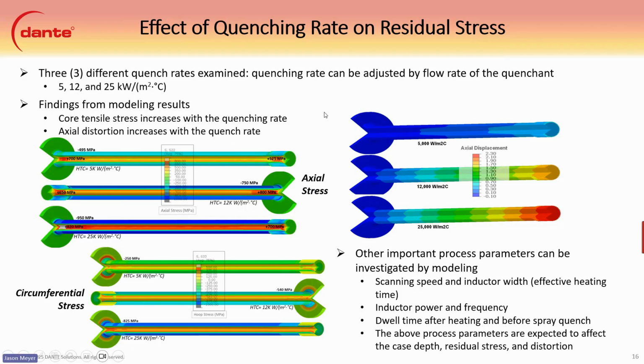We did a pretty exhaustive case study on this project here. So we looked at 3 different quench rates, first of all, since that was one of the levers that they could pull. So we had a reduced quench rate to about 5,000 watts per meter, and then 25,000 watts per meter here. So basically a higher and a lower quench rate based on that baseline model. And the findings was that the core tensile stress increases with quenching rate. So the higher the quenching rate, the higher the level of core tensile stresses that we saw. And then the axial distortion also increases with the quench rate. You can see that with the contour here on the right. With the higher quench rate, the 25,000, we ended up with an axial displacement of over 2 millimeters, 2.3 millimeters, where we had about 2 millimeters for the baseline model, and then the slower quenching rate gave us a result here of about 0.5 millimeter or so in length change.